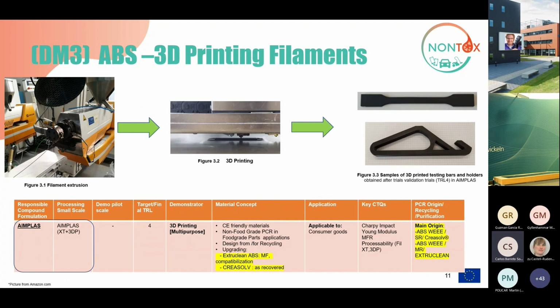The other demonstration case was on 3D printing filaments, where the 3D printing filament extrusion was done first, and then the materials were evaluated in 3D printing. Here the focus was ABS, both from mechanical recycling, devolatilized by Extruclean, and also ABS from CreaSolv. In the case of CreaSolv, the material was used as recovered, while the Extruclean ABS required melt filtration and compatibilization. Here, the main topic was the clogging of the nozzles in the 3D printer that was quite tricky.